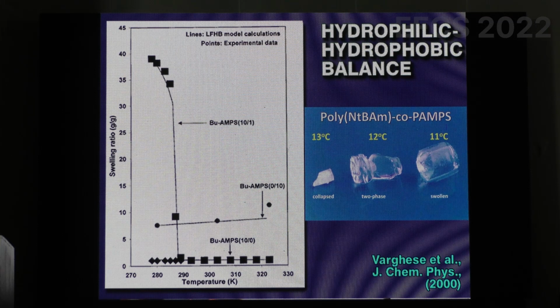And so we started doing more and more stuff. Here is a polymer that has a very hydrophilic group and a very hydrophobic. So these are two polymers, and we have copolymerized them, right? One is very, very hydrophilic and one is very hydrophobic. And so if you take the pure polymers, so this is the very hydrophilic polymer, it has very high swelling ratio and it doesn't change with temperature. And here is the hydrophobic polymer, it doesn't swell at all. And if you change the temperature, also it doesn't swell.